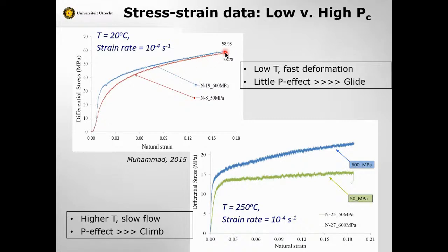That's nearly down in the mantle, which is not realistic. But what you see is the effect of pressure on stress is very small here. At higher temperatures, 50 MPa confining pressure, 600 MPa, and you see there's a much bigger effect. And this actually fits with these models that I just discussed.